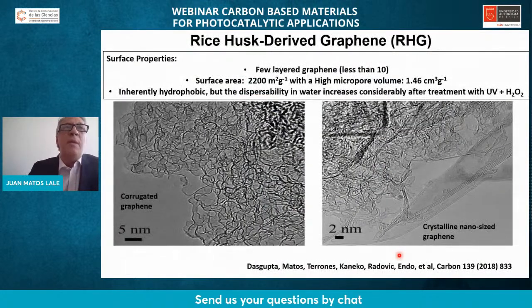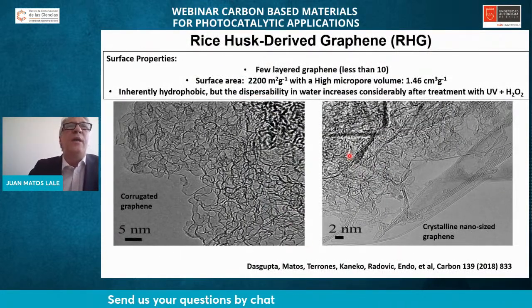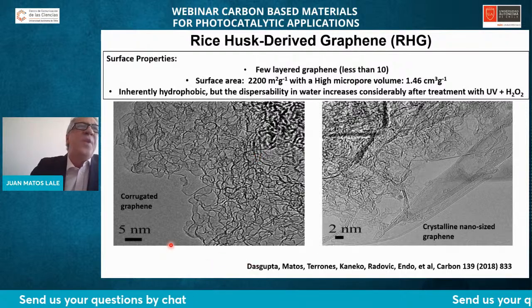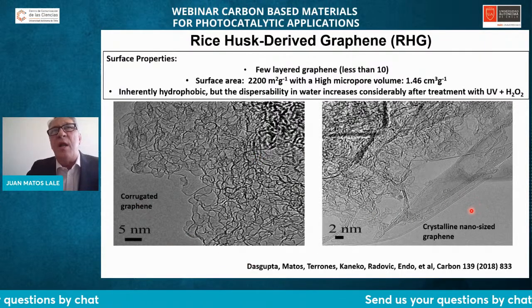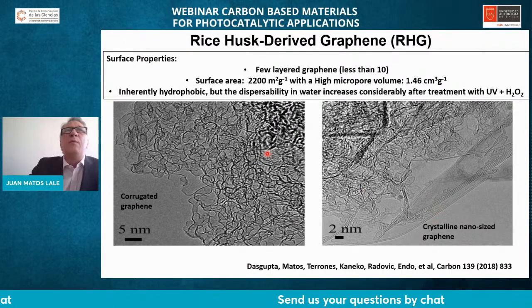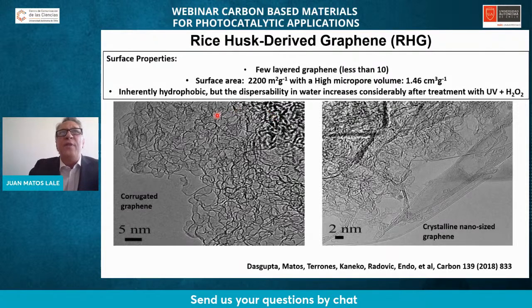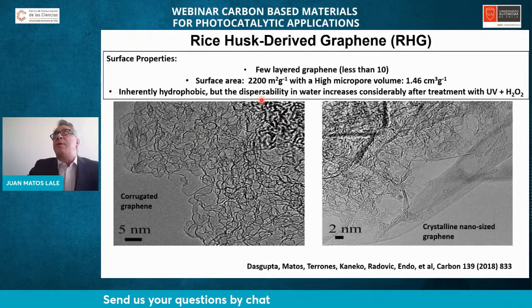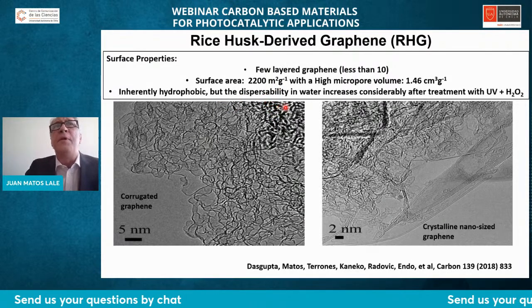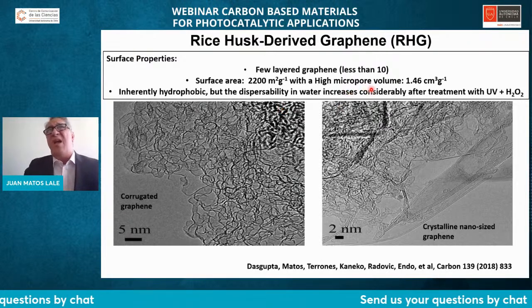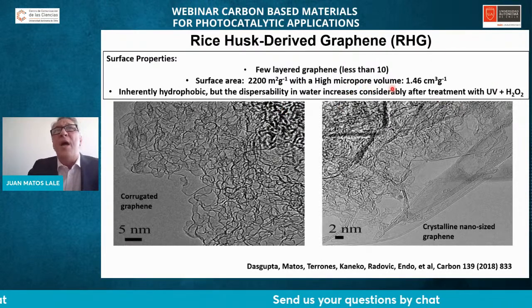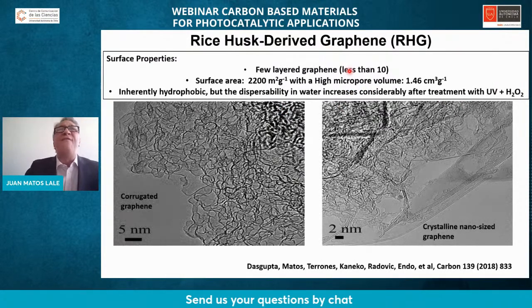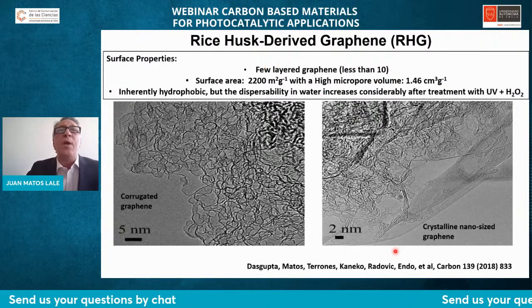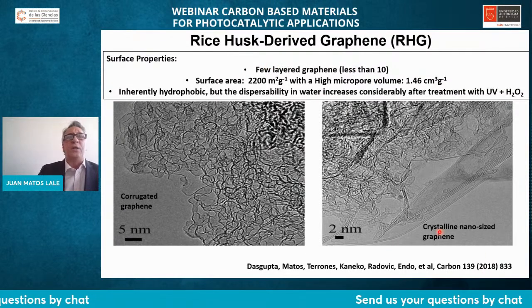But in a more recent work, we have dealt with what we are calling corrugated graphene or crystalline nanosized graphene. And we are able to produce graphene with a very high surface area, even as high as 2,200 square meters per gram, with a very high micropore volume, by using a biomass waste such as rice husk, for example. We published this four years ago.